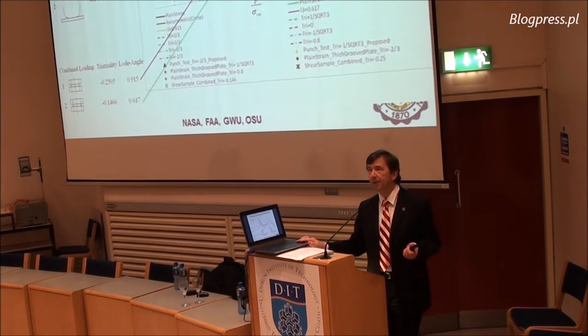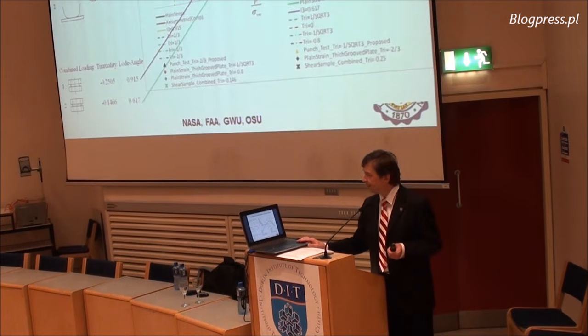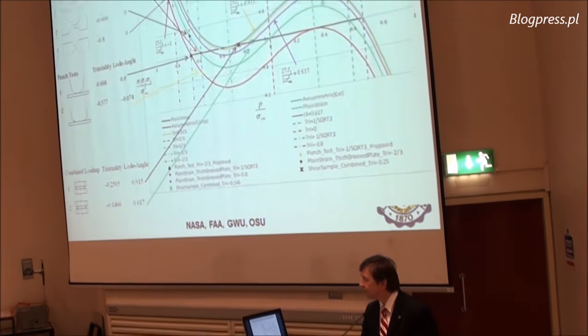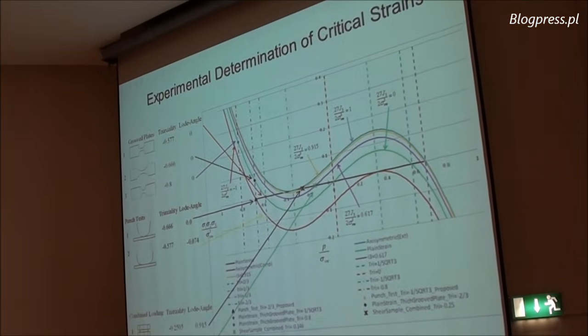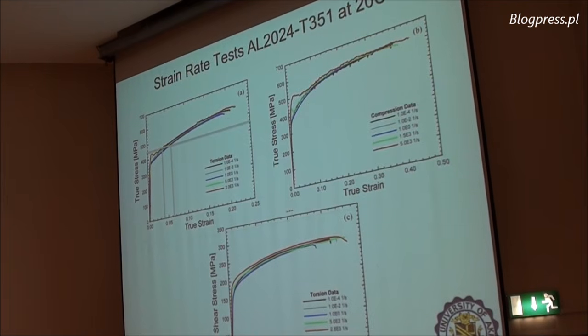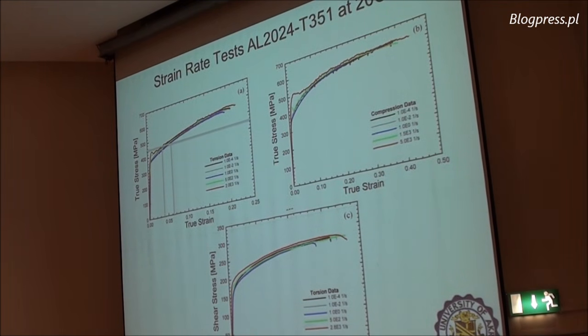So all the aluminum is isotropic, but we found that based on different triaxiality, it behaves differently at failure. And this can be shown by experiments under tension with grooves on the left, 1, 2, 3 test or punch test. And of course that can be done, similarly to composite, using different strain rates. What is interesting is that we can see at 20C that under different rate conditions, the red is the fastest, that the faster we apply load, the stronger the material is, and also not like in composite, the maximum strain is not deteriorated, which is very, very good for aluminum.